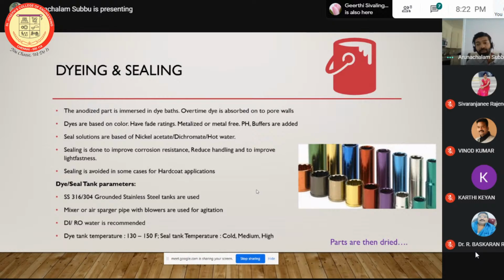Yeah, the sealing is typically avoided in hard coat applications, because in some cases when you apply the sealing, it reduces the abrasion resistance. So it reduces the hardness of the aluminum coating itself. When the pores are open, it's a harder coating. So in those cases, they avoid the sealing. And you can also skip the dyeing step. After the anodizing, you can just directly do the sealing.